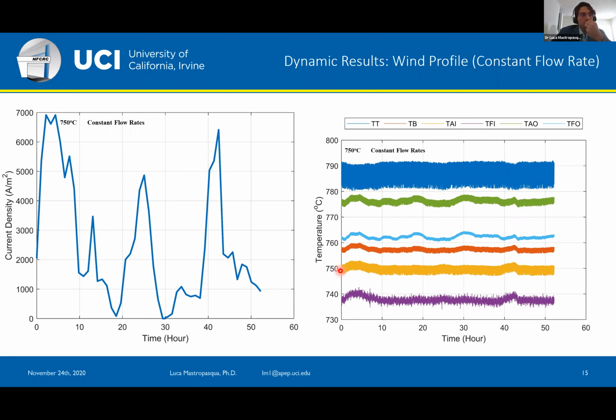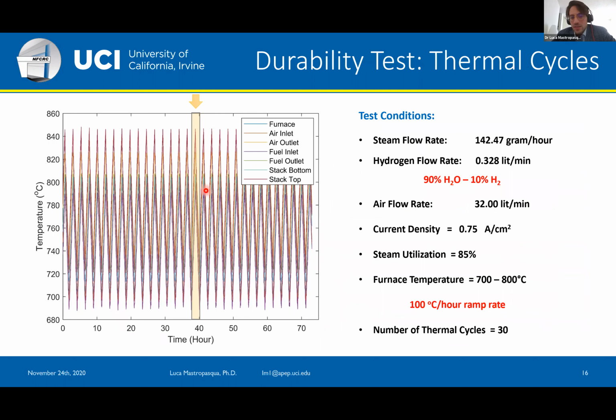So the second question that we have is how much these systems would degrade in the long term if we keep on operating them dynamically, like in this example. In order to answer this question, we did accelerated stress tests on some parameters on the stack, so durability tests. In this chart here, I reported a series of thermal cycles to the stack, where we operated the stack